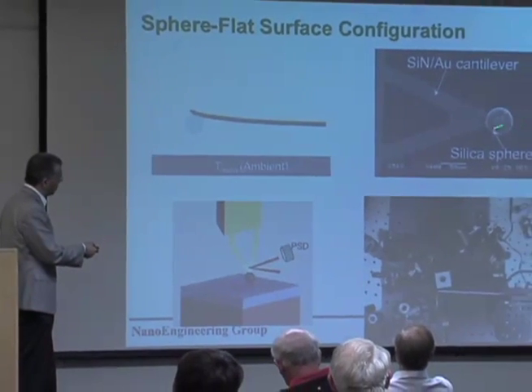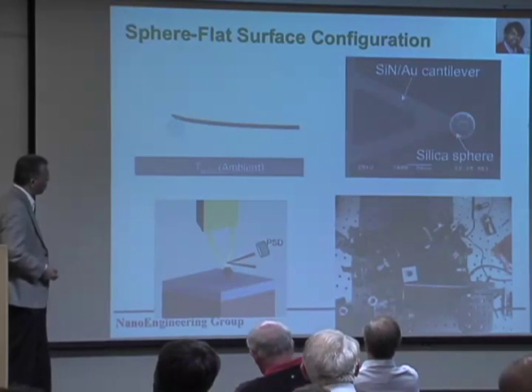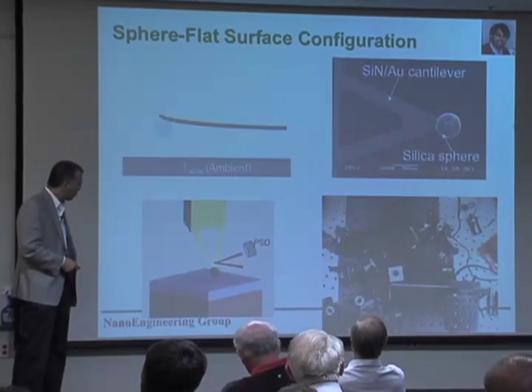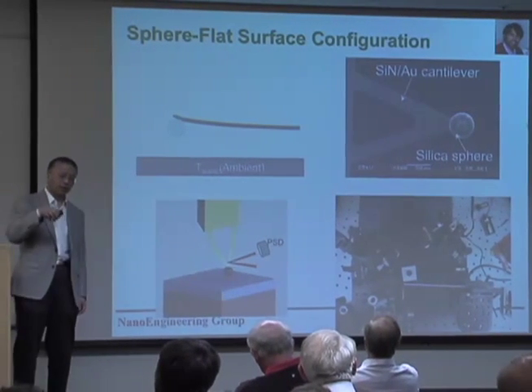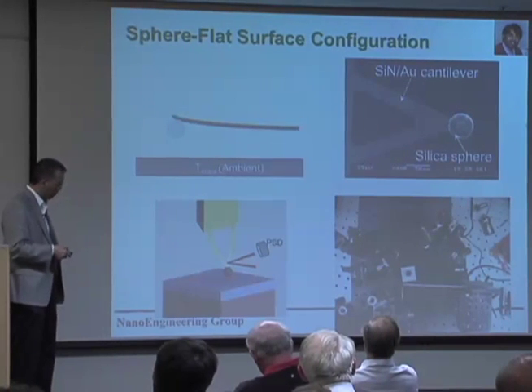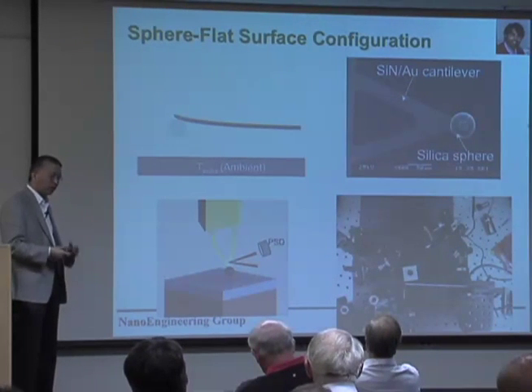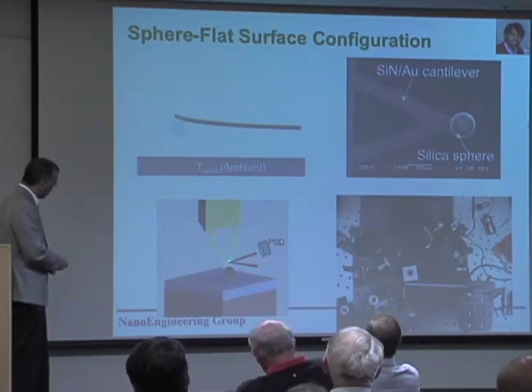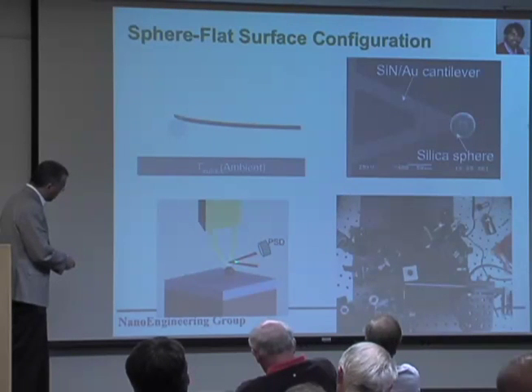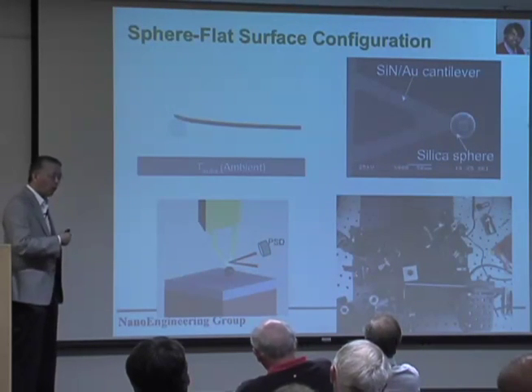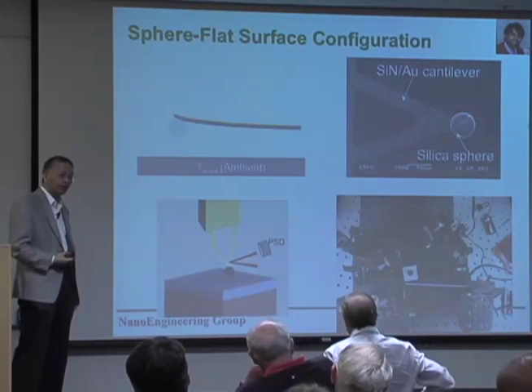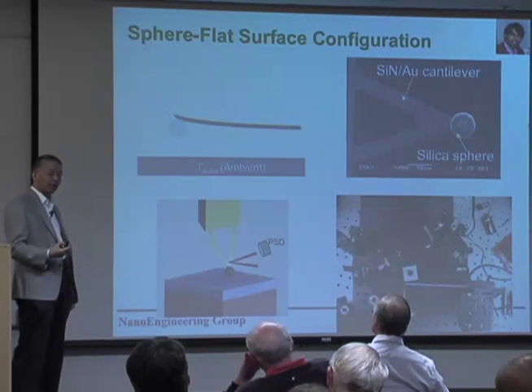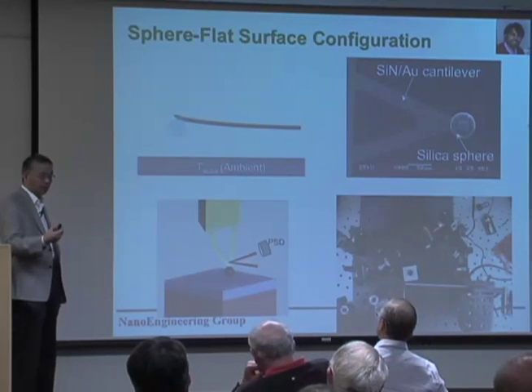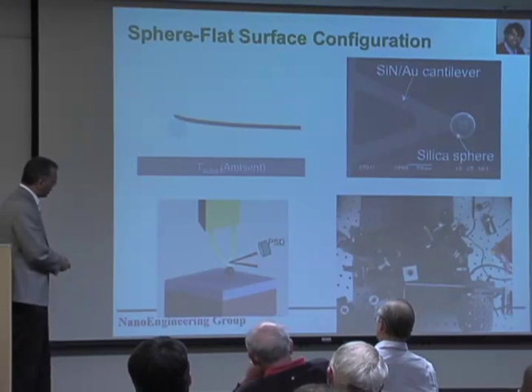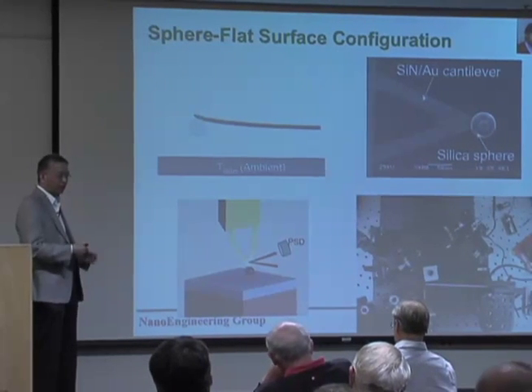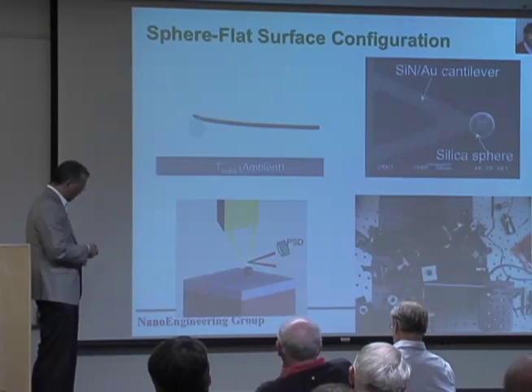We glue a glass sphere onto a cantilever and do basically a force, say the bending, measurement. So it's very similar to AFM. In this case, the laser serves two purposes. One, it heats up the cantilever. When you put this in vacuum, an AFM cantilever heats up about 20 degrees. And second, it measures the bending.